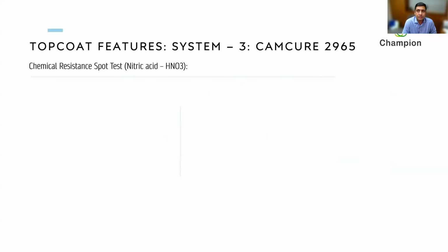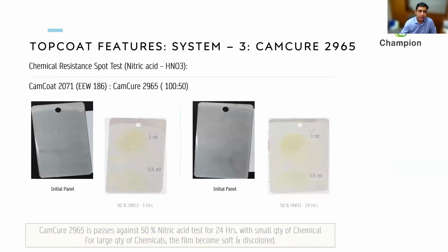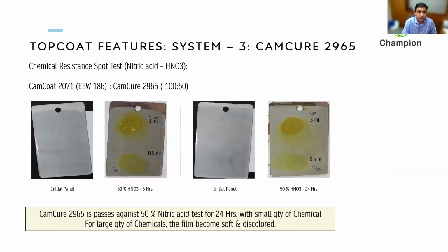We have also checked the same system for nitric acid, just as we had done for 2416. And you will notice from the data and the images that even this system can withstand nitric acid after 5 hours and 24 hours with just a little bit of discoloration. There is no destruction to the film.